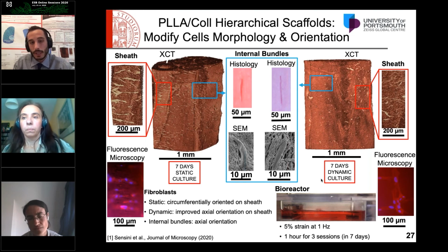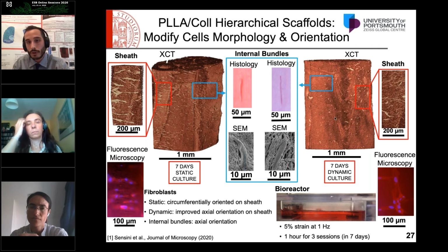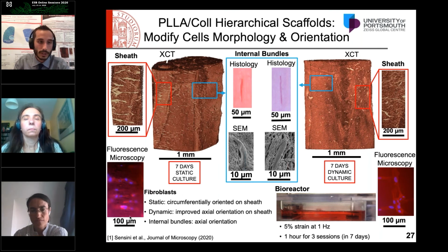What is very interesting, as I started to answer in the previous answer, is that these materials, in this case the PLA and collagen, are so flexible that after cross-linking they allow us to link the Electrospun membranes with the internal bundles, allowing transfer of the cyclic loading to the membrane itself, driving the cell modification too. Have a look here, for example, in the comparison.